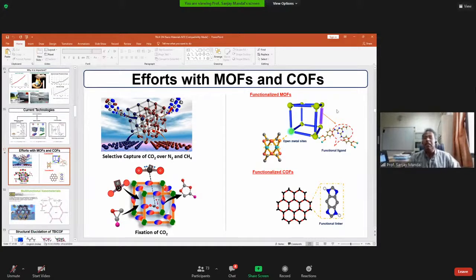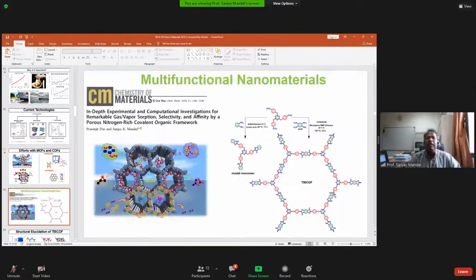So what are the themes to design the MOFs? You can have open metal sites. Suppose you have a paddle wheel structure where you have 4 carboxylates to 2 metal centers, but the axial ligand is open or can be removed. Or you can have functionalized ligands where you have nitrogen or oxygen moieties that can interact. In case of COF, you can have the design where you have NH or N for hydrogen bonding, and of course the pi-pi interaction to do this kind of thing, right? So with this theme, I'm going to show you one from the COF of our research and one from MOF,